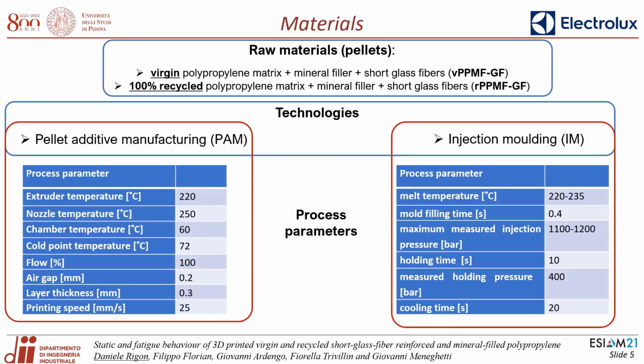So, the raw material is provided as pellets that differ only in the polymer matrix. In the first material, the matrix is virgin, while in the second one it is 100% recycled. For comparison purposes, we compare the static and fatigue test results obtained from PAM with those obtained on specimens produced by injection molding.